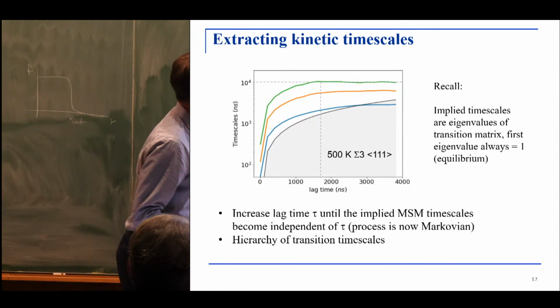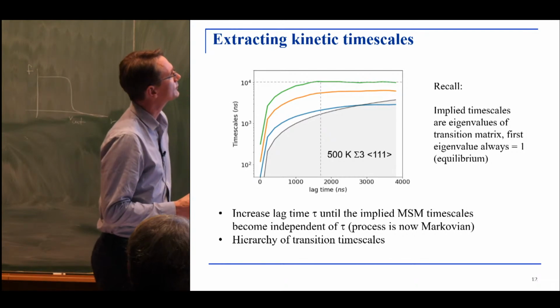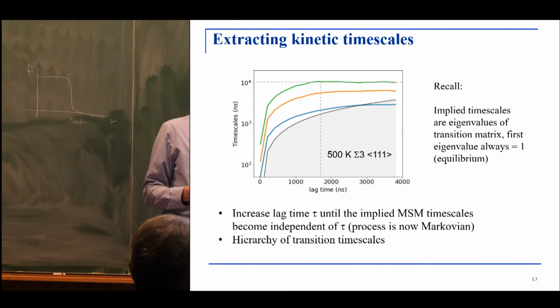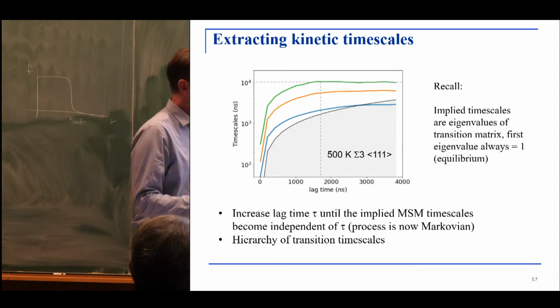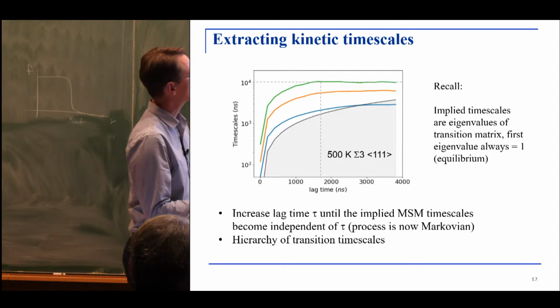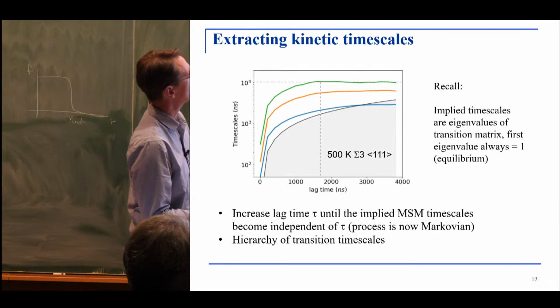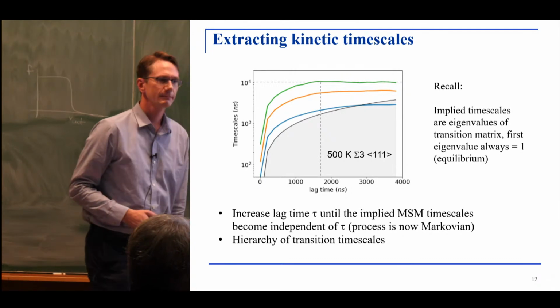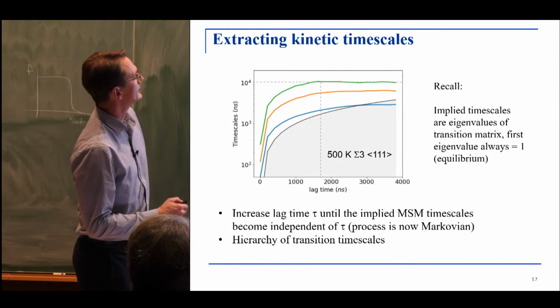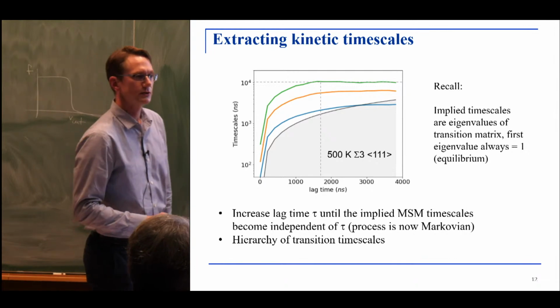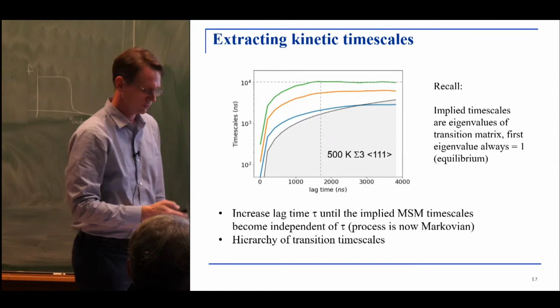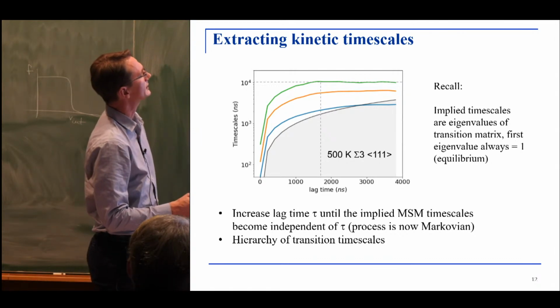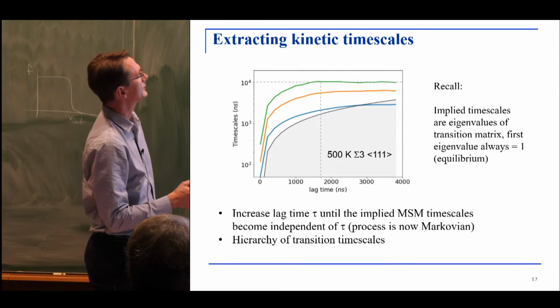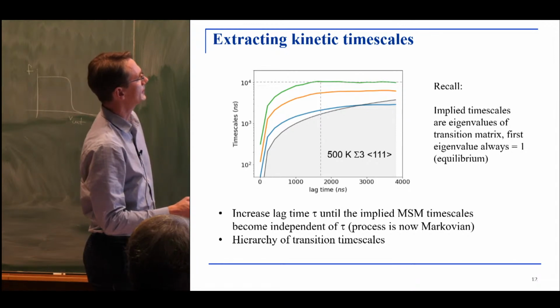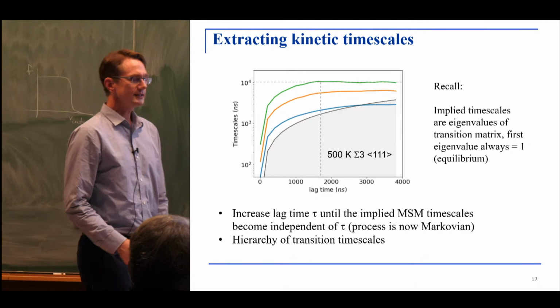The different colors here correspond to three different time scales. We have a four-state model, and there are three time scales involved. There's a hierarchy of time scales that emerges here, and in this case, more or less all three of them plateau at about the same time, which is nice. The black one is just the horizon, where the time scale equals the lag time. So it's just the simulation horizon, if you want. You can see that this crossover occurs at a time which is much larger. The implied time scale, 10 to the 4, is much larger than the actual simulation time, which is about 2 times 10 to the 3 or so. Okay, so this is what we do here.